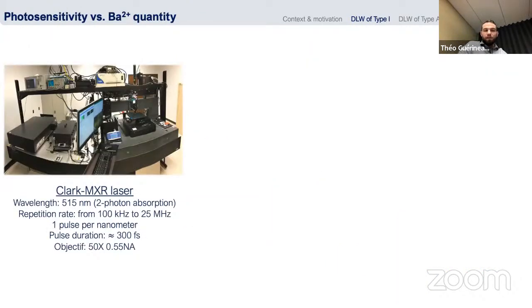So here is the laser that we use, a Clark MXR laser with a wavelength of 515 nanometers and a repetition rate ranging from 100 kilohertz to 25 megahertz. We fixed the number of pulses at 1 pulse per nanometer. The pulse duration is around 300 femtoseconds, and the micro objective is a 50x with a numerical aperture of 0.55.